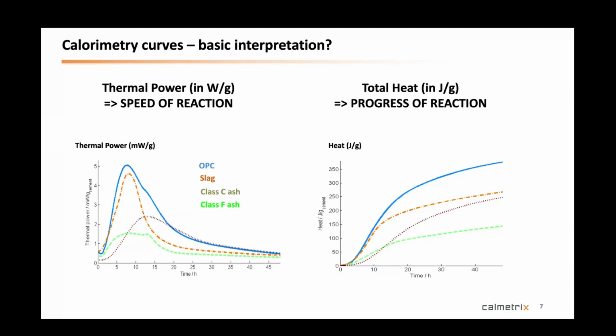In calorimetry curves, you typically see, on the left-hand side, a heat exchange in terms of thermal power. So you have a heat flow that comes from the sample out, and that is measured as it comes out. And you typically see the instantaneous speed of reaction on this. So you see things like setting times, and you see generally how reactive a sample is. And as you can see here, you have different samples from OPC to different class C and F ashes. And you can see how they behave differently depending on the sample type.